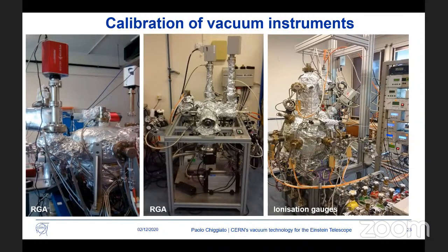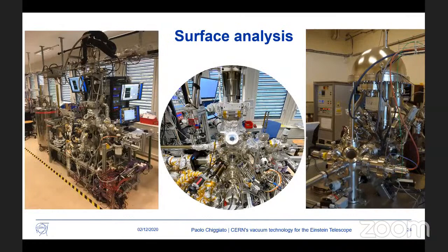We also provide quantitative measurements. This is one of the most important points of our characterization, and this is because we have calibrated vacuum instruments, in particular residual gas analyzers and ionization gauges. Surface analysis is also another important pole of expertise, because with these techniques we can measure the functional properties of materials, in particular secondary electron yield and change of composition when bombarding with electrons and synchrotron light.